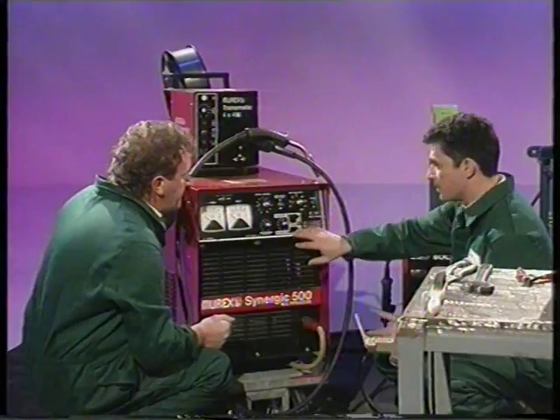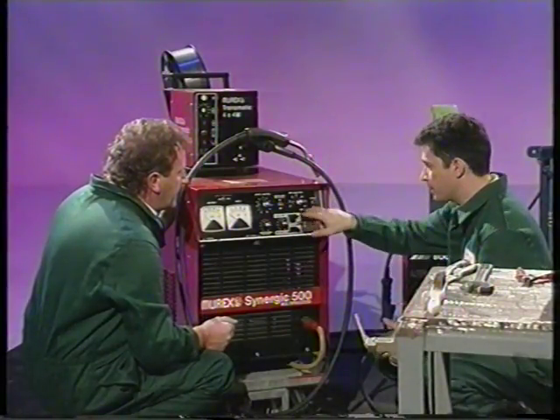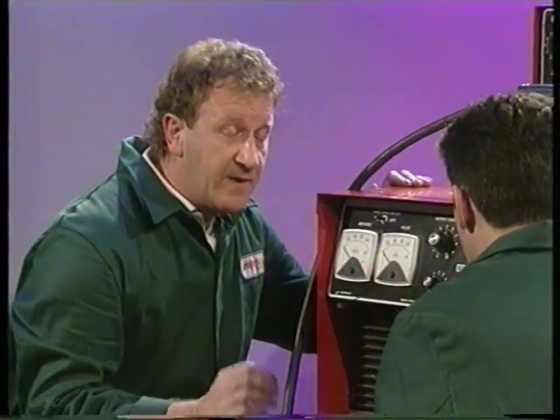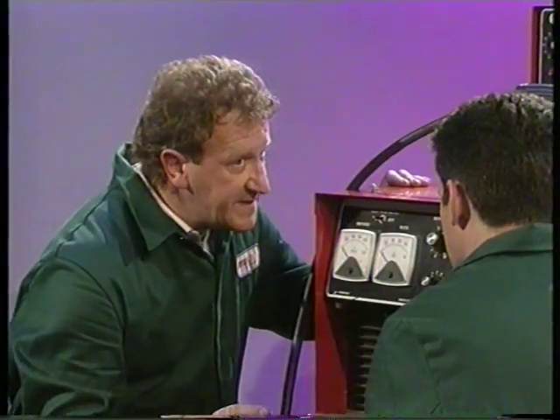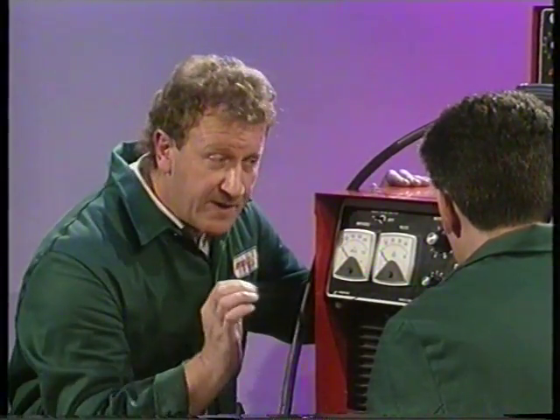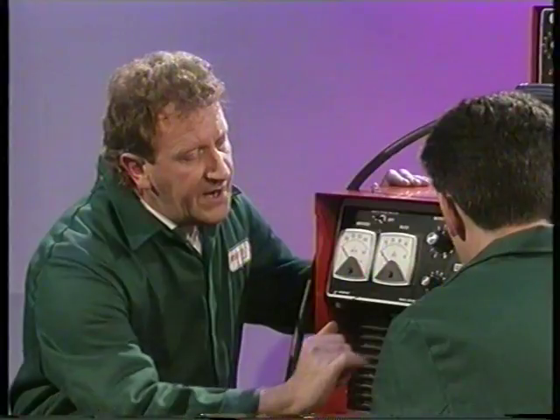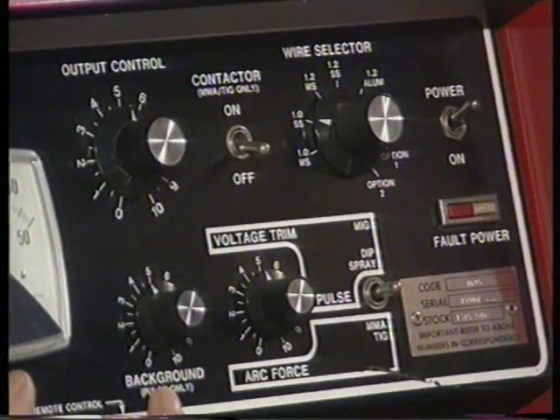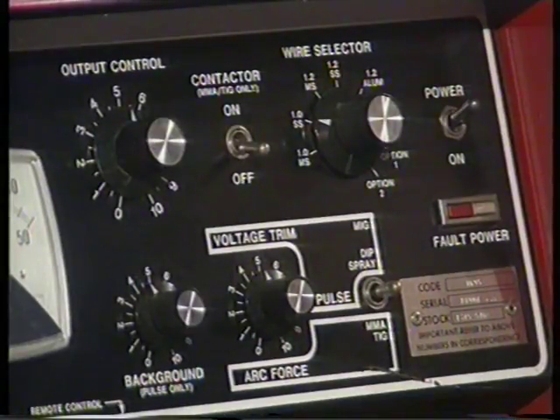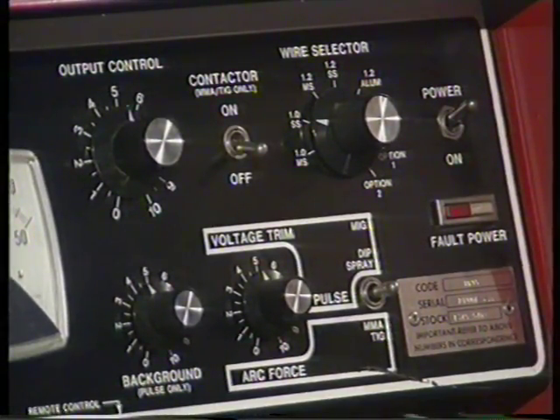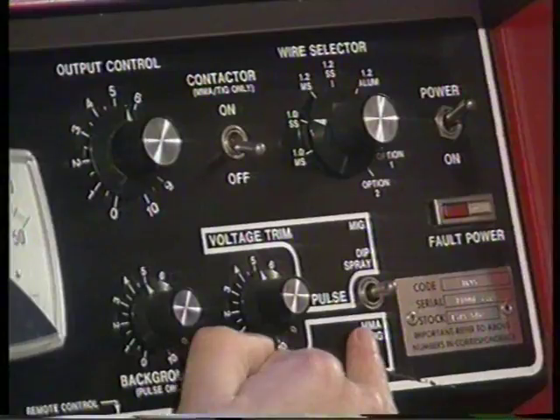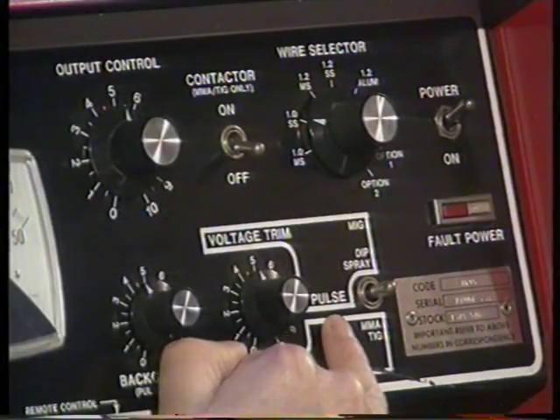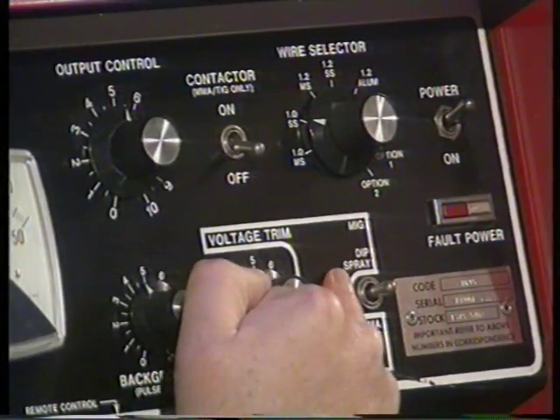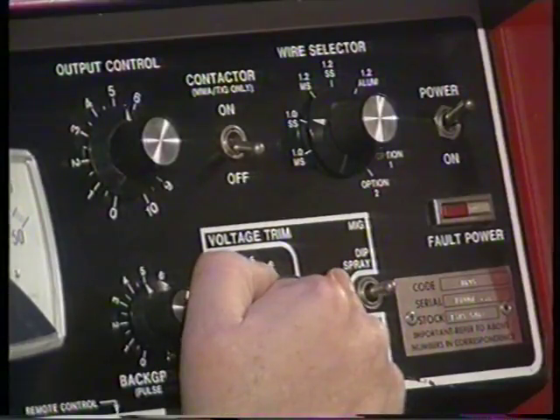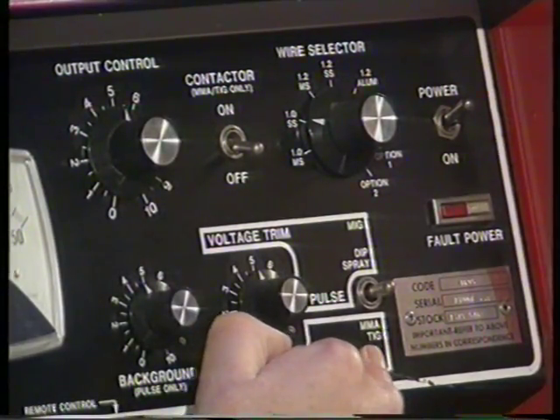Right, so in a sense you're customizing what you're using, you're customizing the program. That's correct, but only by trimming. You're not actually setting the parameters themselves. They're already pre-programmed, but you are allowed to trim the condition. You also have a control here where you can alter the background current if you wish to increase or decrease the background current. The whole process itself is selected on this switch. Here we're selecting pulse MIG. You can see there that we could select standard dip or spray MIG. We could also use manual metal arc or TIG.